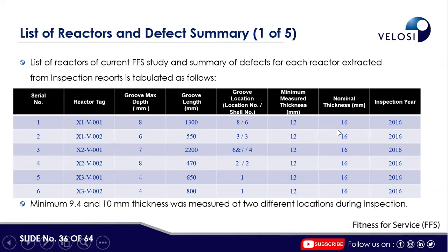So you can see the difference between 16 and 12 is 4 mm, but some groove depths were 8 and 6. So those grooves were basically repaired with weld overlay and considered closed. Otherwise, the FFS scenario for those deep grooves was giving negative results. Inspection year 2016. So minimum 9.4 and 10 mm thickness was measured for 2 locations during the inspection.